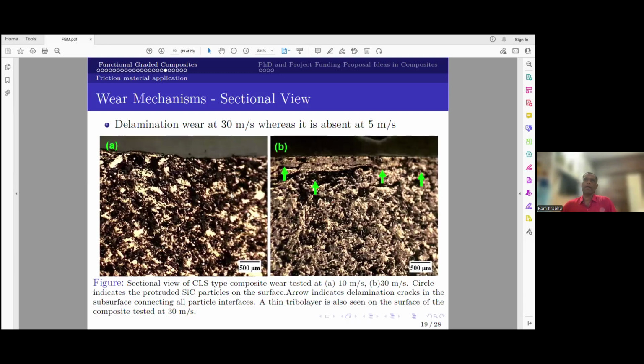just to show you delamination wear, this is a sectional view, like you cut the brake pad cross section and look at it. These arrow regions show the delamination cracks, which connect all the particles and plow out that entire region. Whereas in my functional graded composites you can see thin tribo layers formed on the surface at higher sliding speed, whereas at lower sliding speed you don't see the tribo layer formation. So that's why at higher sliding speed you have better wear resistance, whereas at lower sliding speed you don't, because of the abrasive wear.